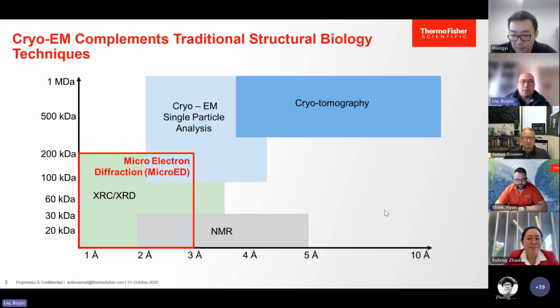So MicroED sort of fills in the resolution gap in the cryo-EM techniques. For single particle analysis and cryo-tomography, we can't really do very small proteins, simply because the imaging is low dose, and we don't really have much contrast for small proteins. But MicroED is actually quite good at solving smaller proteins as well as small molecules. It fills in the gap and also provides slightly better resolution than single particle analysis, and some benefits from diffraction.